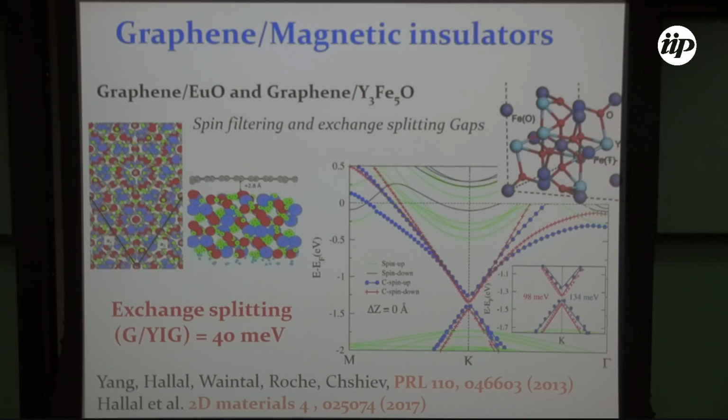It's a gigantic amount of computer time to put graphene on a magnetic insulator and to see how the interface will relax, and what will be the impact of this magnetic insulator on graphene. What will be the size of the exchange coupling field, which will result in opening a gap, splitting the bands, and just showing that graphene becomes different, becomes spin imprinted by the proximity effect.